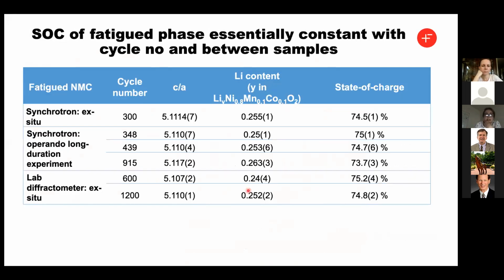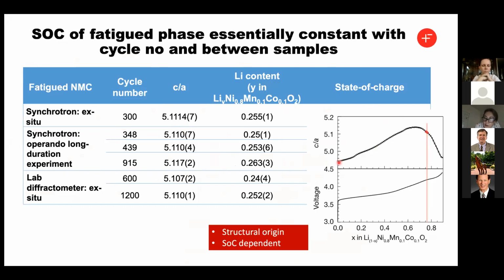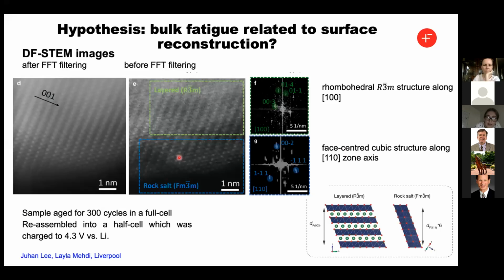But instead, what we noticed was that the fatigue phase always failed at the same state of charge of about 75%. And that's at a particular C/A ratio. I talked about this idea of the C parameter going up and then collapsing, and it's where it starts to collapse at about 0.75. And what's interesting about that is that it correlates with the formation of a rock salt on these materials. I introduced at the beginning this idea of nickel 4+ not being very stable. It loses oxygen and it forms a nickel oxide rock salt, NiO, on the top.